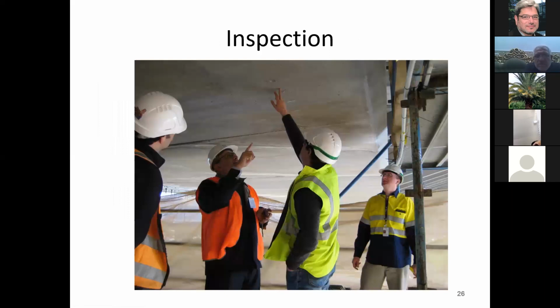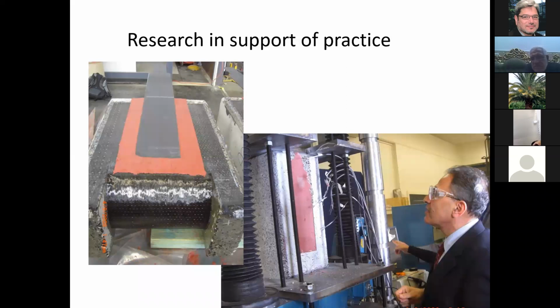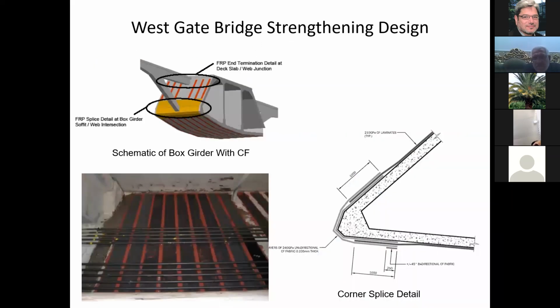We have inspected this bridge. We have done extensive inspection to see the existing damage in this bridge, particularly in the form of cracks, because cracks have to be closed, they have to be sealed, particularly if they are active cracks, before we endeavor to strengthen. We carried out an extensive research project that took about 4 months in order to come up with a viable structural retrofitting system in the form of FRP, especially for this bridge. And this was done as the designers were designing the FRP or assessing the bridge, and they wanted us to come up with an FRP system that's going to be very effective.